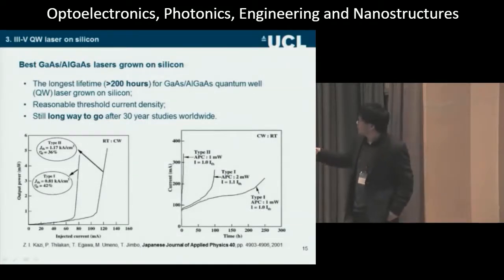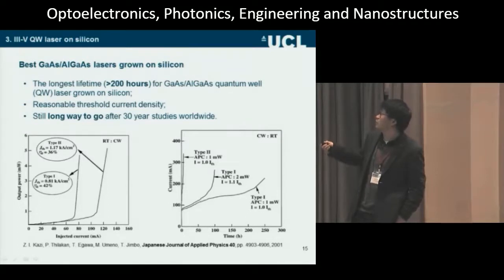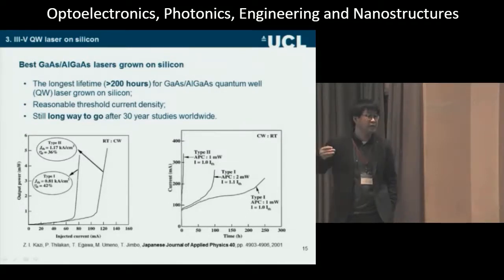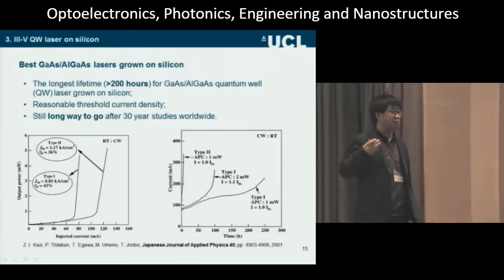This one was published in 2001. They got a room temperature CW laser. The threshold is 1.1 kA per centimeter squared. It's not too bad, but the problem is the lifetime. The device only works around 200 hours and then dies. With this kind of lifetime, you can never put this kind of device in your practical system.